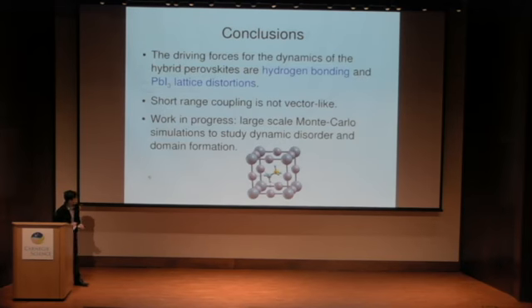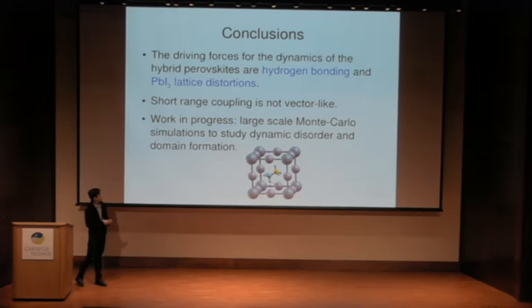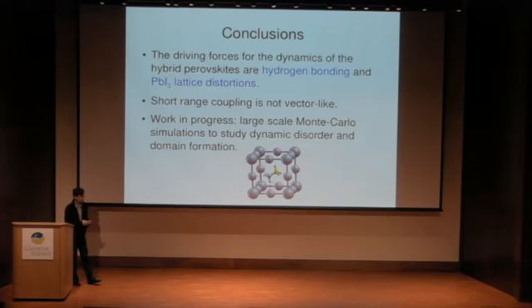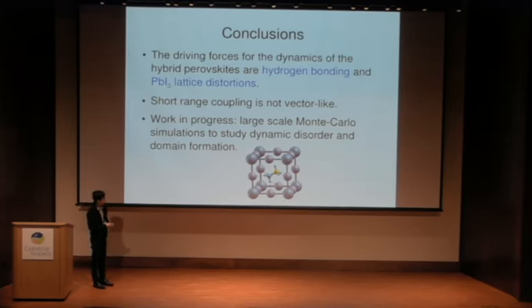So with that, maybe I can make the conclusions. I hope to have shown today that there are two factors which are important in these hybrid perovskites: the hydrogen bonding and the presence of lattice distortions. Now, probably the point that I would like to make today is that the short-range coupling is actually of a complicated form, and it's not a vector-like coupling. One has to be careful to take into account the proper nature of hydrogen bonds. We're doing right now Monte Carlo simulations to examine how this plays out at finite temperatures, including dynamic disorder.